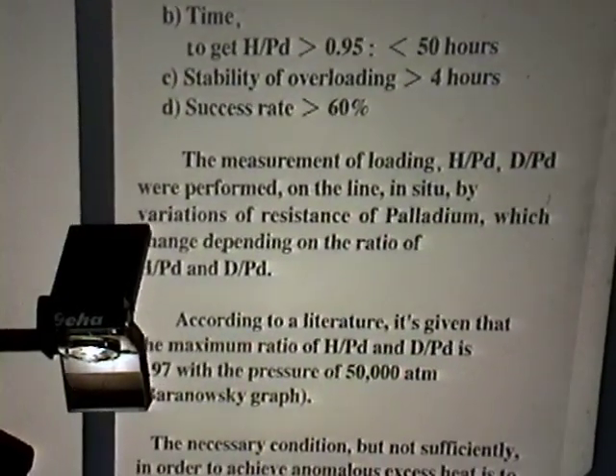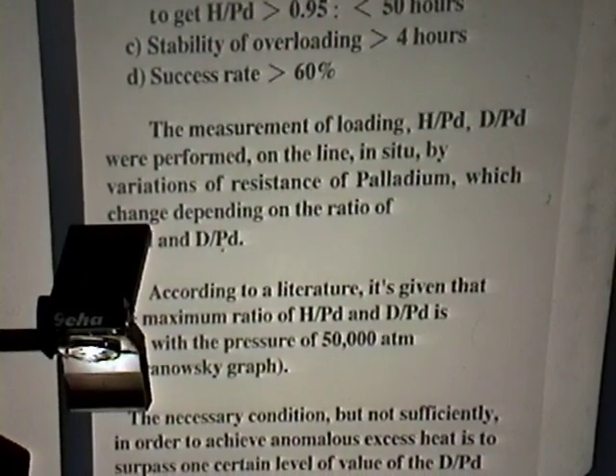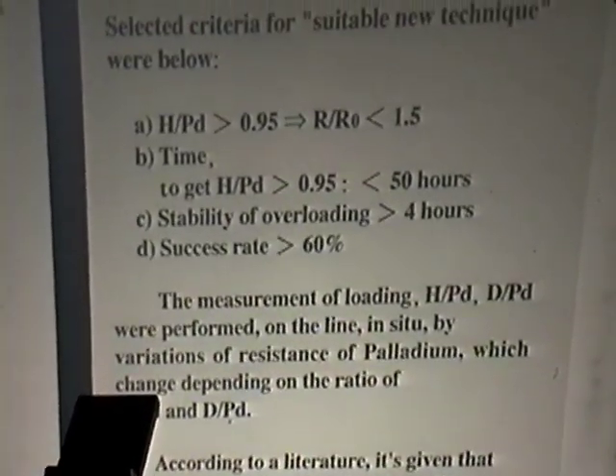So, because of the problem of low reproducibility, we decided to study new techniques to get overloading. We decided to quit for the moment using deuterium and lithium. We want a new procedure to get a hydrogen loading larger than 0.95. The time to reach the maximum should not be too long, less than 2 days, 50 hours. And the stability of the overloading should last at least 4 hours, in order to make some reliable measurements. And we want the overall success rate of our procedure to be larger than 60%.